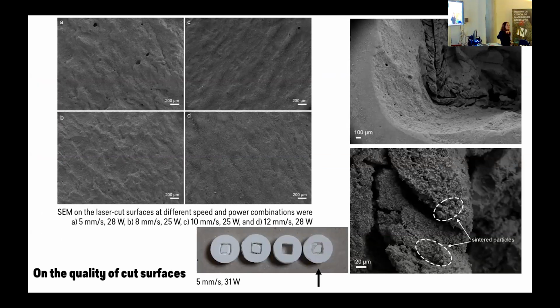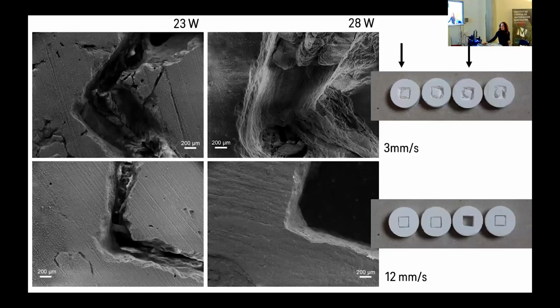So we have done lots of surface characterization to see how the material behaves once it interacts with the laser. We have observed some sintered particles and such. These are also single pass. It is not that we have gone around the same region several times, these are just a simple pass. And these materials are 1 centimeter thick. So you can cut these materials with a CO2 laser 1 centimeter thick. One of the findings that we had was that if you use a slow laser speed, you are not doing good to the material. It is going so slowly that it is sintering the edges, but you have to go rather fast in order to have these cuts on the material.